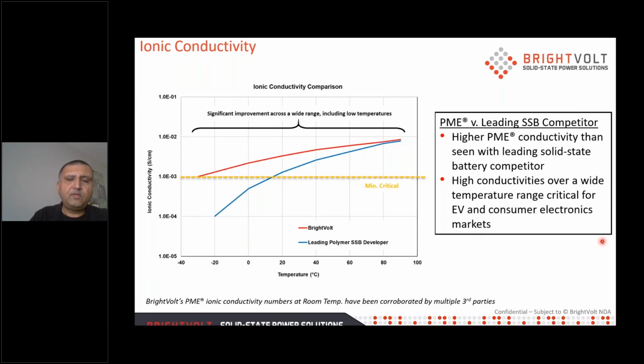So if you look at essentially a PME to replace or do the function of a separator and electrolyte, there are many different properties that you would be looking at. I'm going to share just one or two critical ones in today's talk. So the first and foremost is ionic conductivity. And so what you're seeing here is ionic conductivity data. It's a logarithmic axis on the vertical y-axis, plotted against a wide range of temperature, again going from -30 up to 100°C. And what you'll notice here is, in the case of the PME, it delivers a minimum of at least 1 millisiemens per centimeter of ionic conductivity all the way down to -30, which I think really differentiates this from some of the other competitive polymer electrolyte solutions that we have seen in the market today.